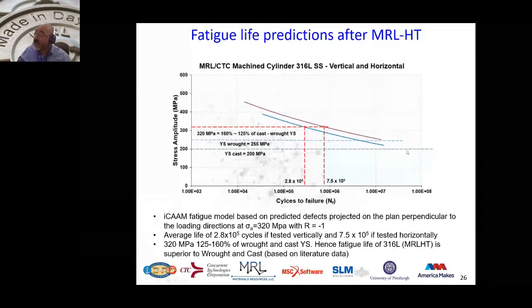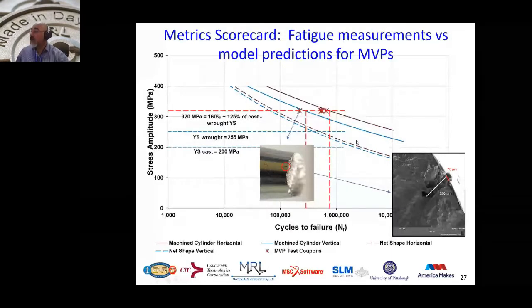One of the interesting things we'd like to share with you: when we did the predictions, they cover both machined as well as net shape material. The difference is where the defects are. So for the machined and electropolished, it was embedded defects. The net shape was mainly related to surface defects, and the dotted model covers the prediction we did for the net shape, which is mainly related to surface defects.